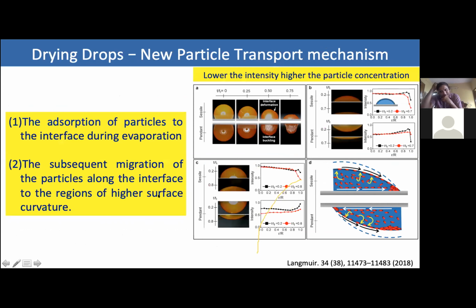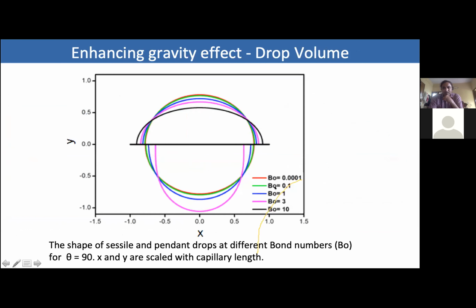So in the interest of time, I'm just going to quickly mention that the reason why we get different deposit patterns is because of the induced deformation of the drop. Okay, so what you see is a plot of how the drop shape varies as a function of Bond number. Bond number essentially tells us whether the drops are deformed in the presence of gravity or not. If you have a small Bond number, the surface tension forces are dominant, and the drop remains spherical or a spherical cap. However, if the Bond number becomes higher, the drop shape is deformed, right?